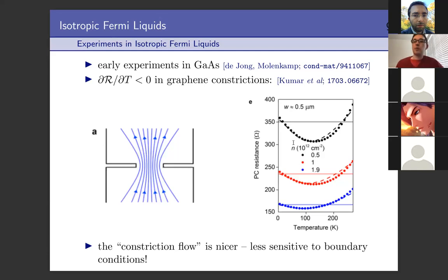One reason that we're confident that this is the effect we think it is, is that these straight lines are actually predictions for what the flow in the ballistic limit would be. At very low temperatures, we are very close to the ballistic prediction for resistance. Then to have this kind of super ballistic transport, where the resistance is below the ballistic limit, that's a clear signature of these viscous effects.